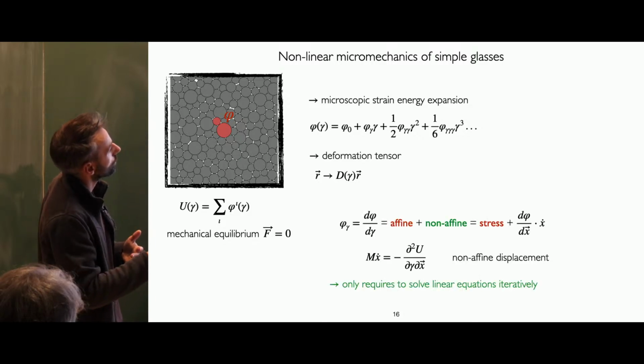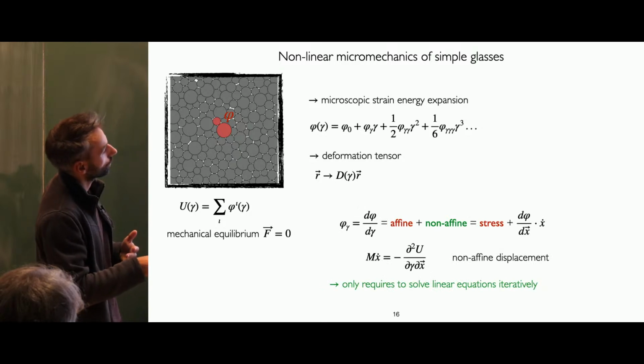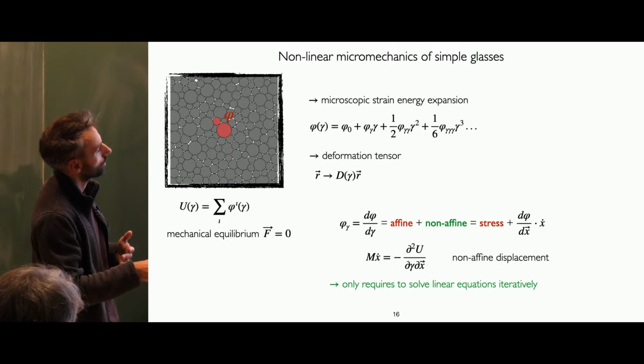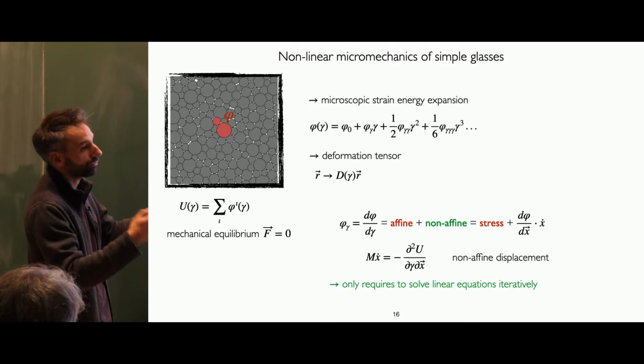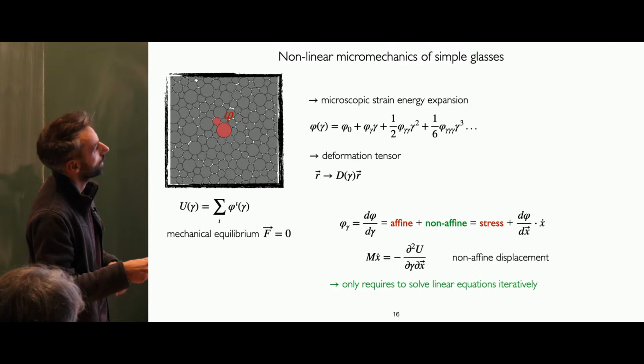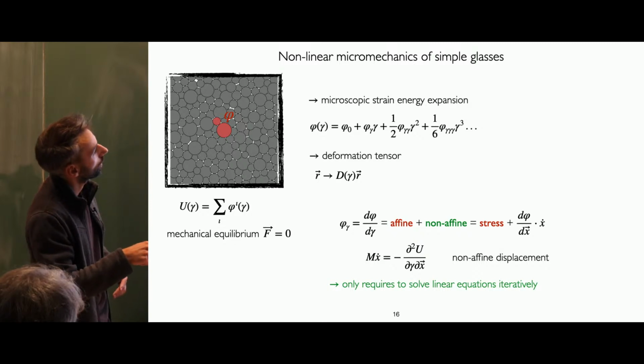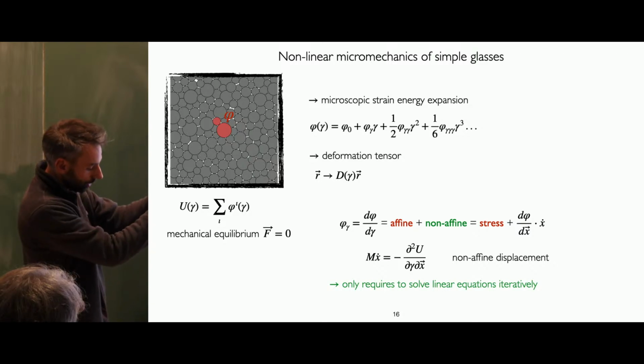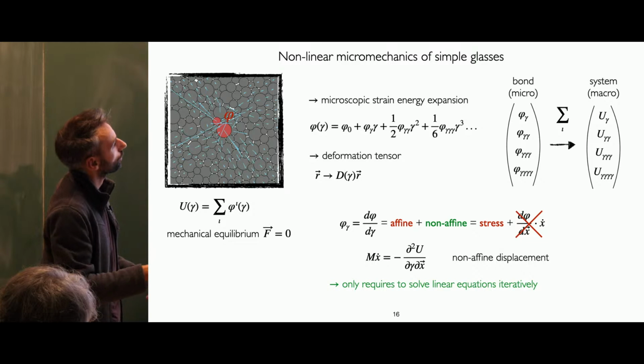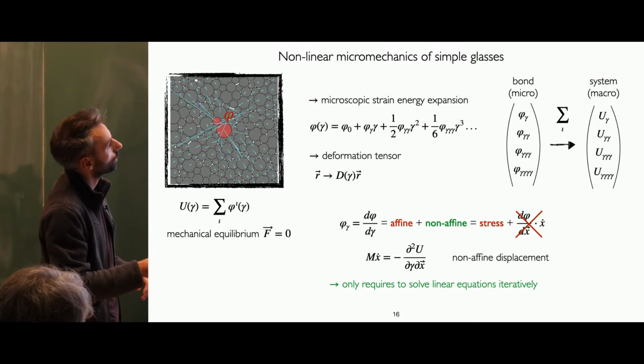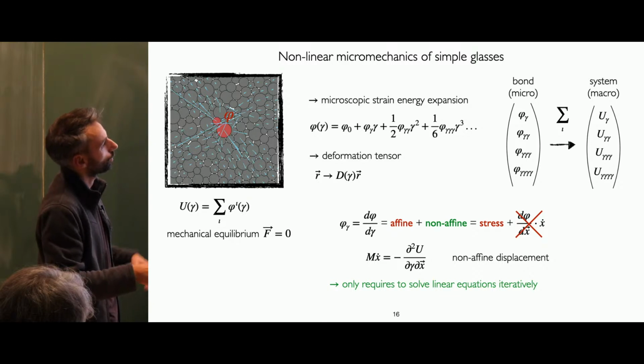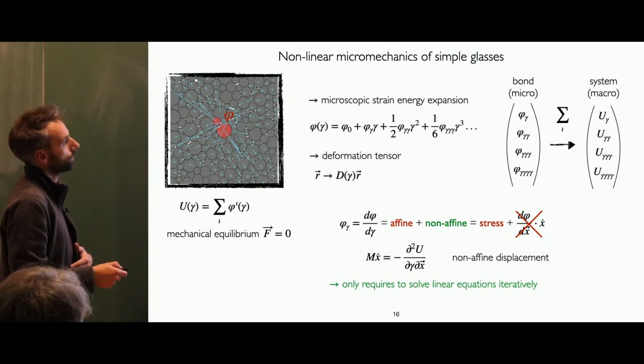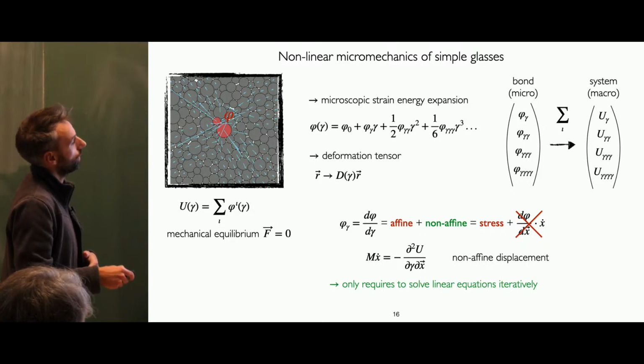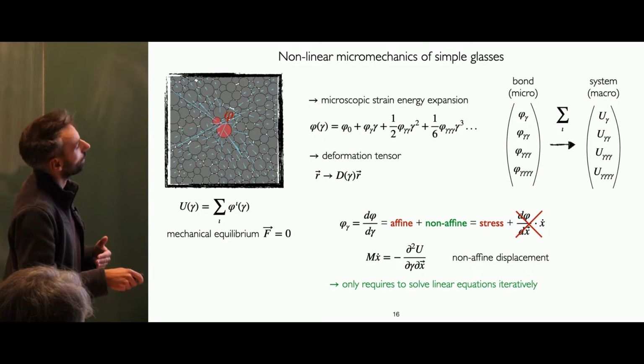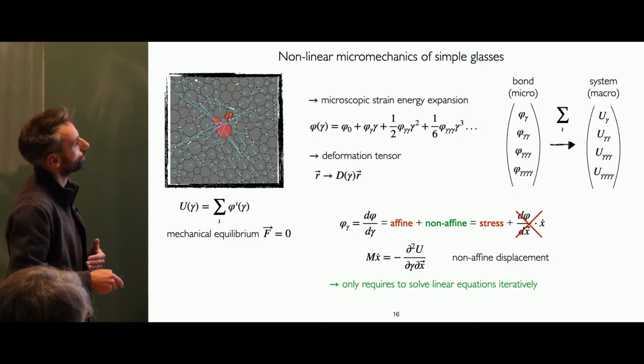And so for each coefficient, what you will have to find is, you will look at the total deformation. So there will be an affine and a non-affine part. For example, for the first coefficient, the affine one, you might know it, it's just the stress. But there will also be some non-affine response when you want to restore mechanical equilibrium. And so now for each bond, you know how the energy of 2 particles locally will change. So you can, of course, get the nonlinear coefficients at the bond level, but you can also sum them and get the macroscopic strain energy expansion of your solid. And then try to connect how those non-affine parts connect with the population of soft modes.